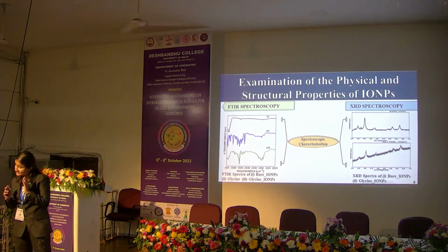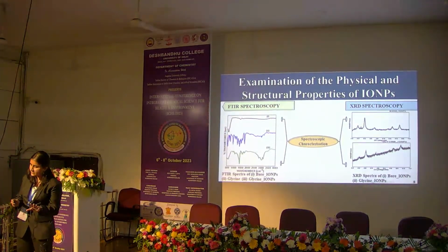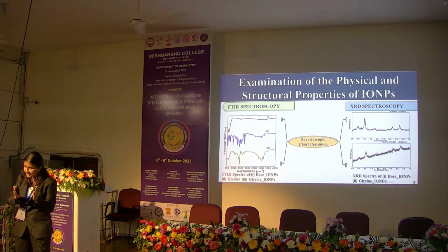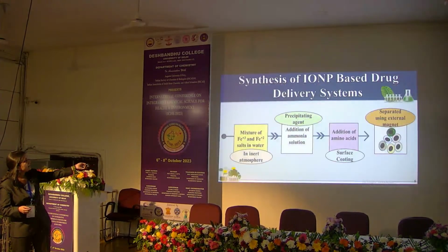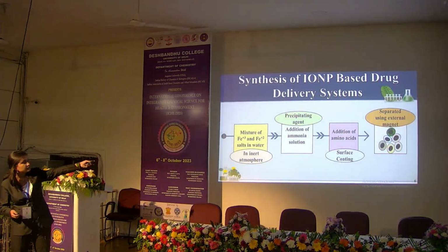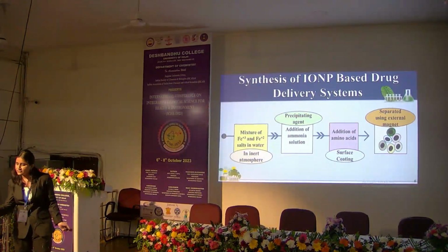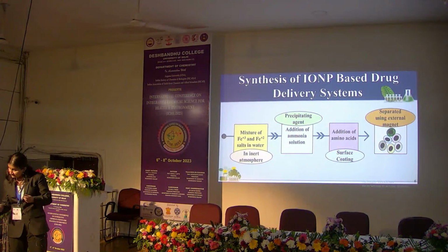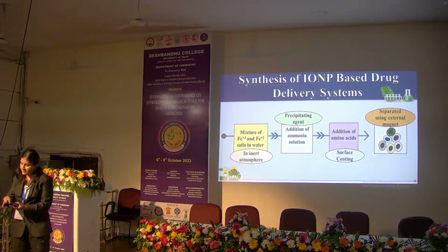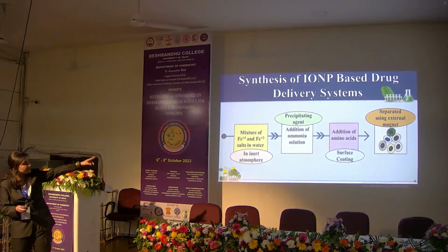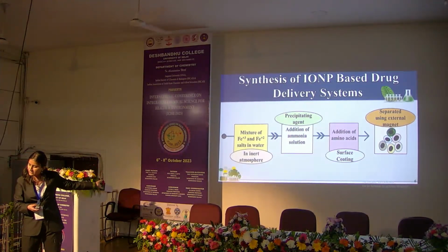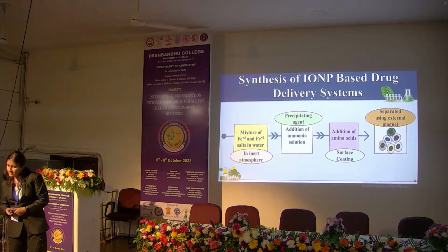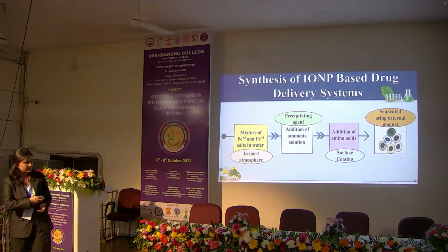No, sir. If we are synthesizing bare iron oxide nanoparticles, we are not using anything, just iron plus 3 and plus 2 salt, and I am using a co-precipitating agent. I am using ammonia solution as co-precipitant, and there is no amino acid. So for the coating, it is just one step where we add amino acid. So in the bare iron oxide nanoparticle, there is no chance of amino acid.